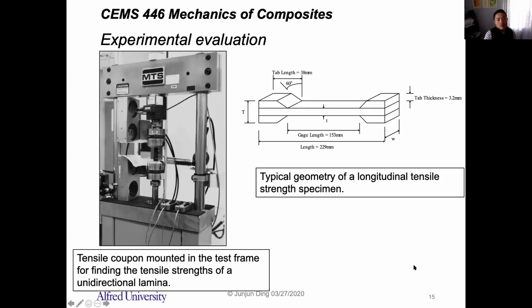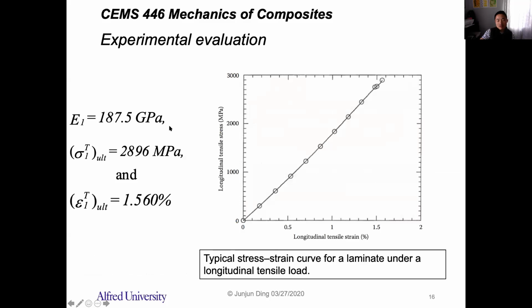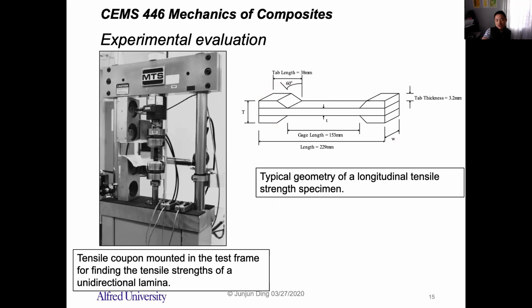And if you want to use the experiment to check the ultimate strength, you can use this tensile mechanical tester to pull this dog bone shape of the composite. Right? So in this way, you can directly measure. You can use the strain gauge to measure the strain on the composite, on this sample. And this stress can be measured by this machine. So in that way, you can measure the ultimate stress of the composite in the longitudinal direction, right?